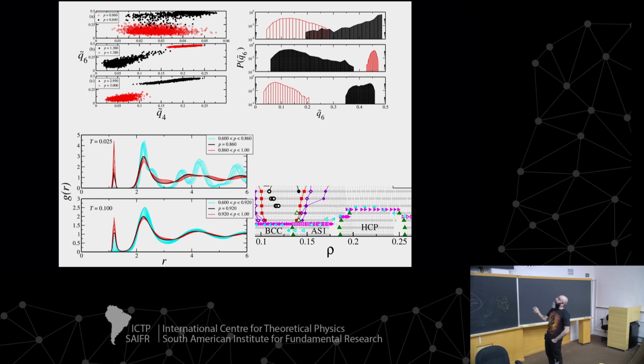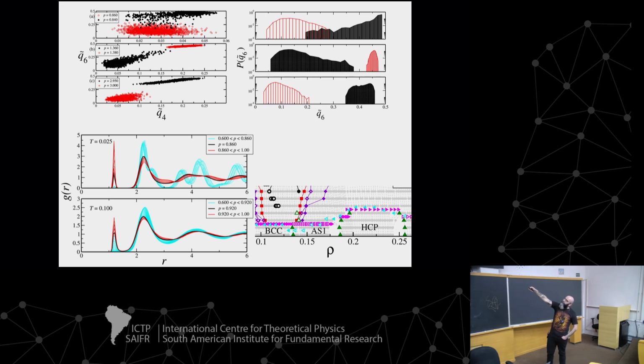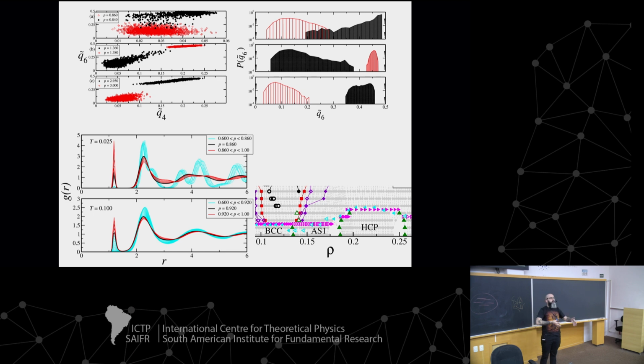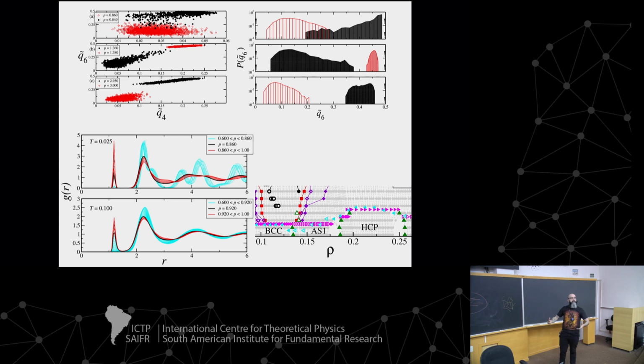And also, we could see here Q6 against Q4, the orientation of the system. If I go from the amorphous phase to the HCP solid phase, or from HCP to the other amorphous phase, in these two cases you can see that in one phase you don't have any points on top of the other one. We don't have this overlap of points. Important: each point here is the Q6 and Q4 for each molecule in our system. We were using 10,000 particles, so we have 10,000 points here. So it's not the mean value, it's the value for each particle along the simulation. So you can see that here you don't have any kind of overlap.